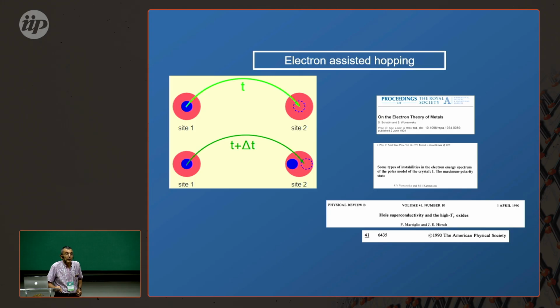That you can define as some kind of electron-assisted hopping. Depending on how many electrons you have, the hopping between Wannier functions changes, and that creates these huge distortions in the band structure. This was way back already proposed by Jorge Hirsch in connection with high Tc superconductivity, as a criticism of